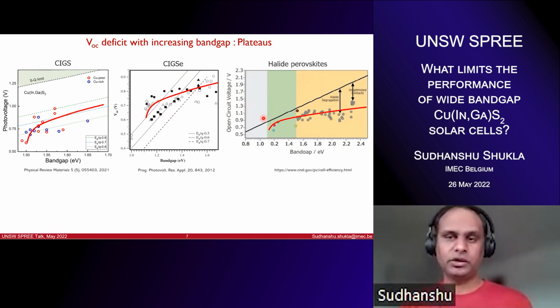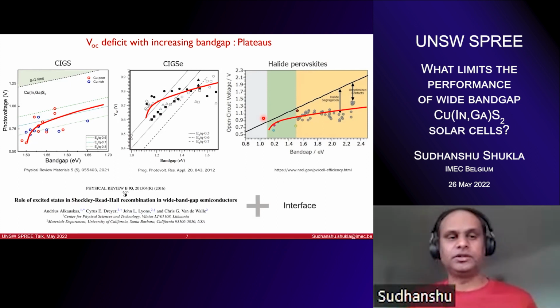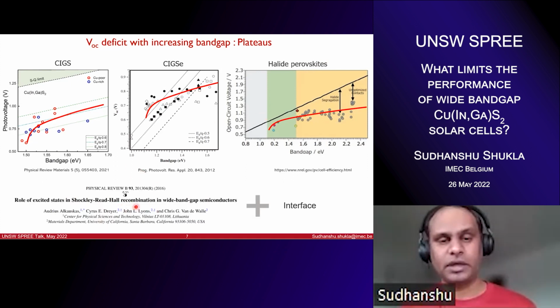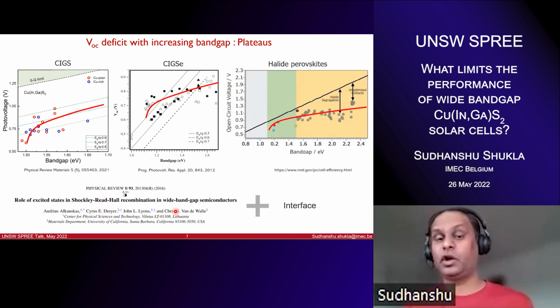So how to think? There is something profound going on. There's something common in these different materials, a pretty generic observation. For that, I will refer to this nice study, and I would highly encourage everyone to read it: Shockley-Read-Hall recombination in wide bandgap semiconductors. It becomes an extremely important and limiting factor when you are dealing with wide bandgap semiconductors. But at the same time, you have to be very careful about the interfaces as well, because when you increase the band gap, it's not just the bulk that is giving you the losses, but the interfaces that you then need to alter, because the electron extraction and hole extraction layers have to be optimized accordingly, which sometimes we don't, because we use the same buffer layers even if the band gap is high.